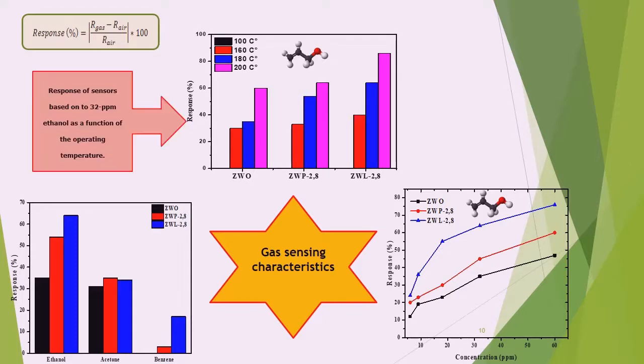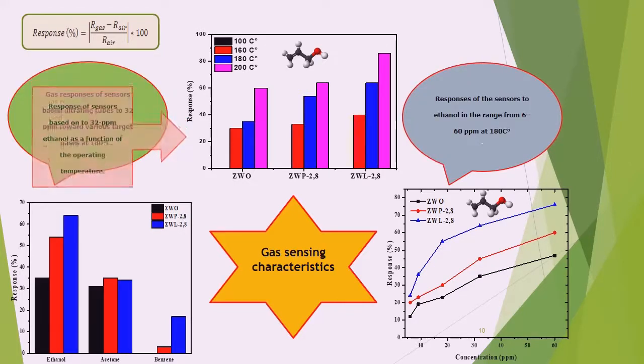The sensors with lavender and paraffin exhibit enhanced response for the tested gases compared to zinc oxide without oil, with a higher response of 64 percent to 32 ppm for zinc oxide with lavender, which was two times higher than zinc oxide without oil at 180 degrees Celsius. Regarding zinc oxide with paraffin, which presents an enhancement in the response toward the three gases, we observed affinity toward acetone. Therefore, it is very clear that the sensor based on lavender could be selective to ethanol.